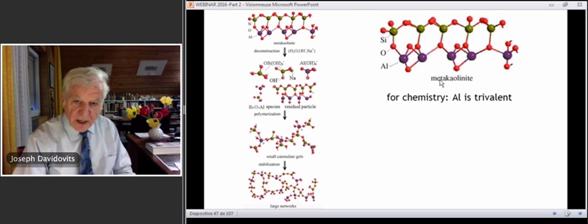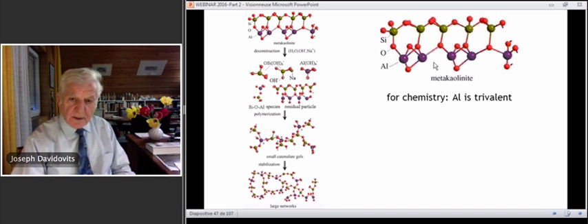This is the structure of metakaolin. There is no OH in this structure. Aluminum should be surrounded, covalently bonded to 3 oxygen. It is trivalent. What we have here, aluminum, 1, 2, 3, 4 oxygen. It is tetravalent. This is a nonsense. This does not exist. This structure is false.